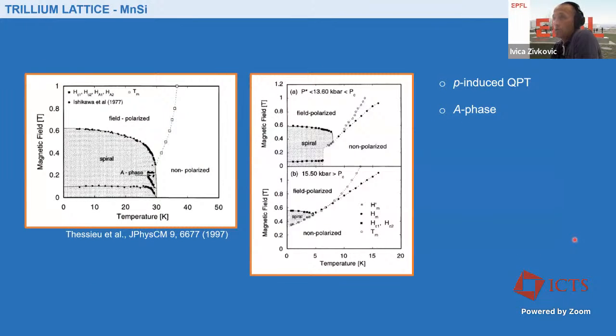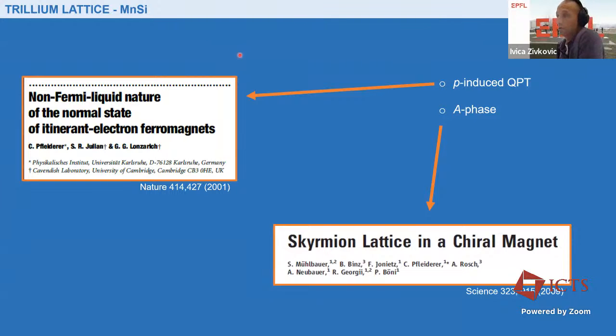Okay, so before going into the double trillium lattice situation, we can look into what happens in the single trillium lattice. And the best-known compound forming that lattice is manganese silicide. For this compound, more than one lecture can be given. So here, just the highlights: it has been found that you can have a pressure-induced quantum phase transition, and then there is this mysterious A phase. And then it turned out through a series of high-profile articles that this pressure-induced quantum phase transition supports non-Fermi liquid behavior.